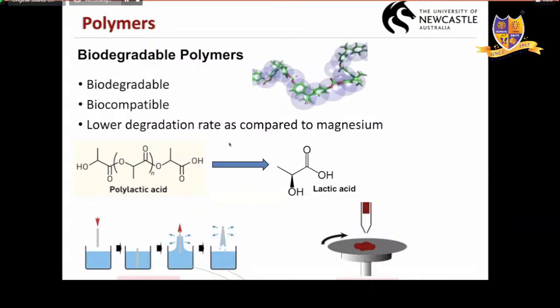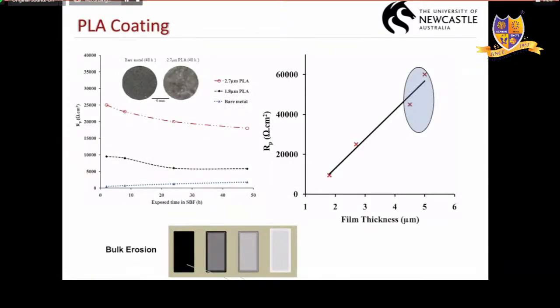We looked into two types of coating. First is the dip coating. The dip coating produced a very thick coating. Because of that thickness, the adhesion of that coating to the metal was quite poor. So we had to rule that out, and we went on to do a spin coating, where the polymer dissolved in a solvent is dropped onto a disc, and that's how spin coating is done. It produced a relatively thin coating, which is what we were after, and the adhesion was quite good as compared to the dip coating.